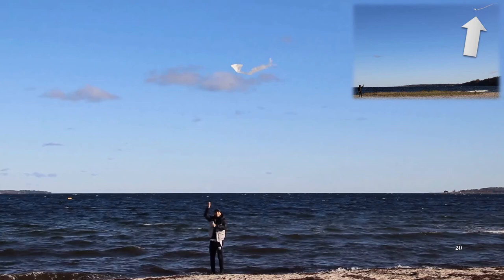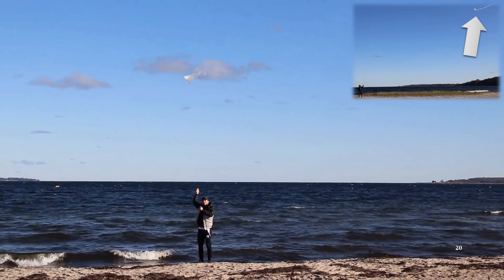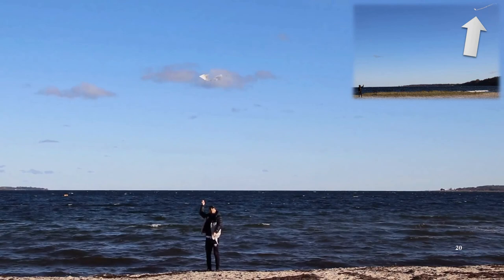The kites were tested for multiple times at wind speeds up to 50 km per hour. The kites, which was designed to fly in extreme weather conditions, could withstand loads applied by strong winds with no sign of damage or failure.